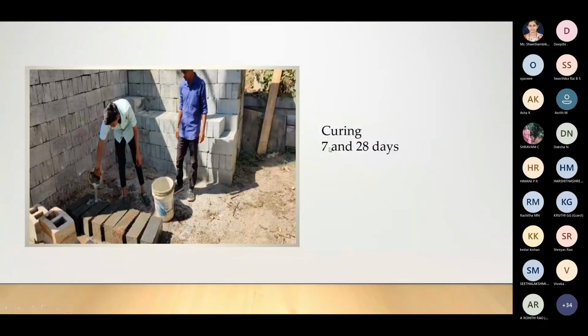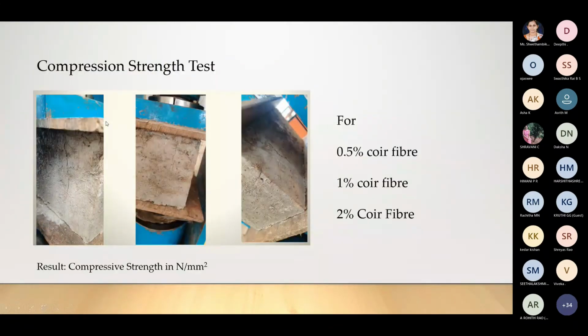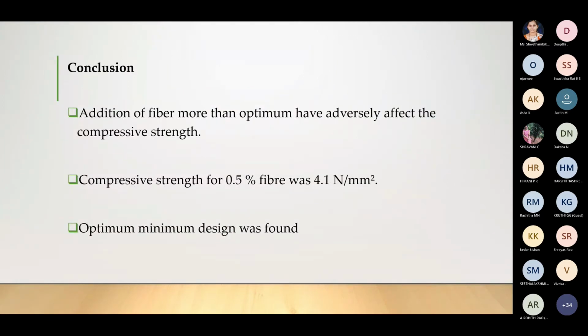Then curing has to be done for 7 days and 28 days, adding water, and before testing, it has to be properly sun dried. Then they tested the compressive strength for 0.5% coir fiber, 1%, and 2%. They got the result of compressive strength in Newton per mm square. What they have concluded is that addition of fiber more than the optimum adversely affects the compressive strength. If you add more fiber, strength will decrease.